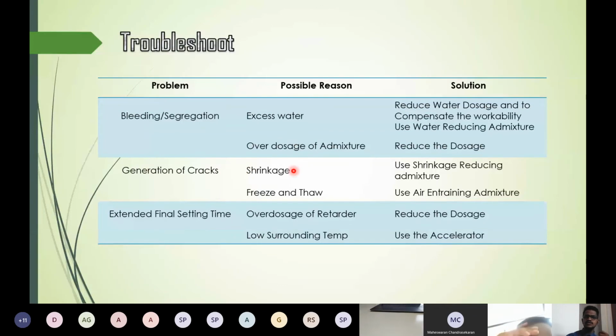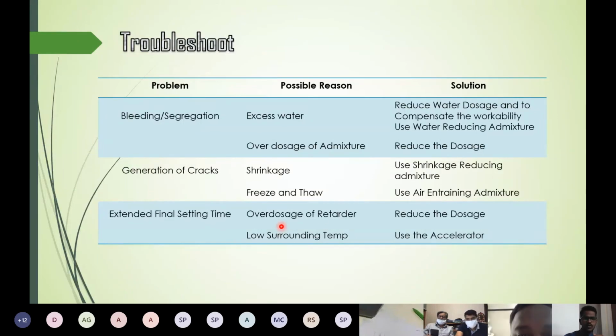Next problem is generation of cracks. The possible reason is shrinkage. So you can use shrinkage reducing admixture. The second is the freeze and thaw condition, and for that you can use air entraining admixture. Another problem is the extended final setting time. The reason can be overdosage of retarder. The solution is to reduce the dosage. Another possible reason is low surrounding temperature. Low surrounding temperature also affects the setting time of the concrete, which can extend the setting time of concrete. So for that, use the accelerator.